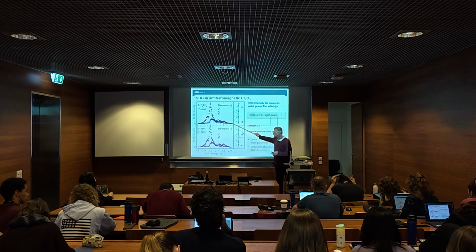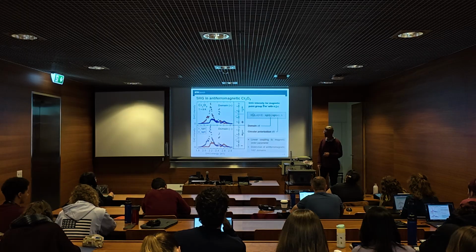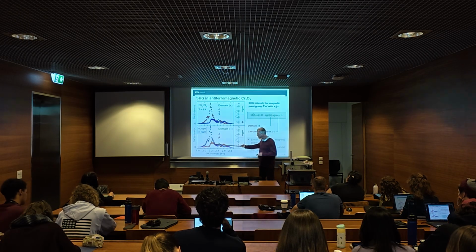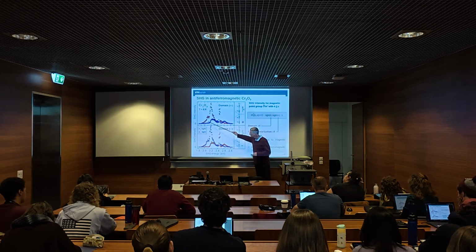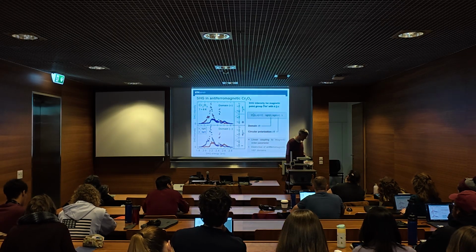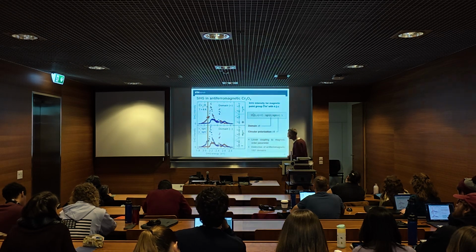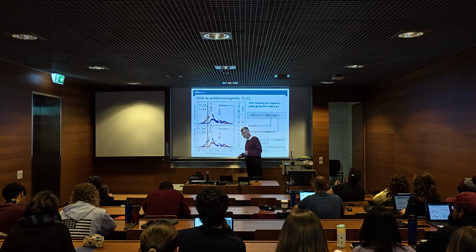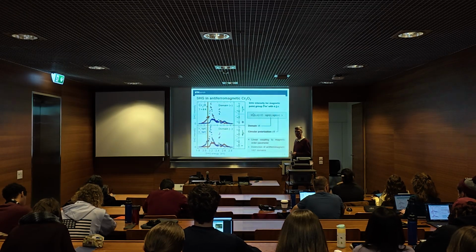So that was then a demonstration that you can really see antiferromagnetic order with a very large contrast between the domains. So look at the contrast that you have, from right here to right there. Very large contrast between the domains. And then you can just say, okay, I now take light at this photon energy, 2.1 electron volt, that's orange light, and I image my sample in this frequency doubled light.